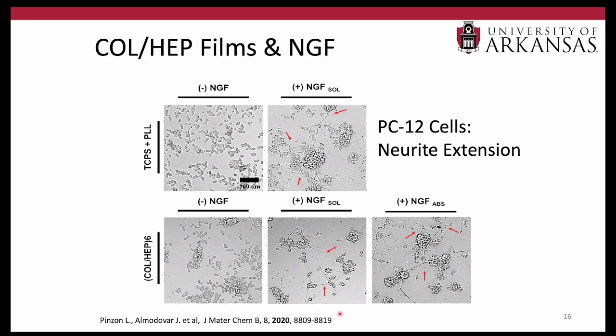Well, when we do the same on our coatings, first of all, we see that the cells do attach. So that's pretty good. But then when we add NGF, whether we add it in solution or incorporate it as part of the coatings, we see really long neurite extensions. And that's quite favorable. That tells us that the cells really do like these surfaces, and that the NGF is perhaps acting in a better way than on our control surface.